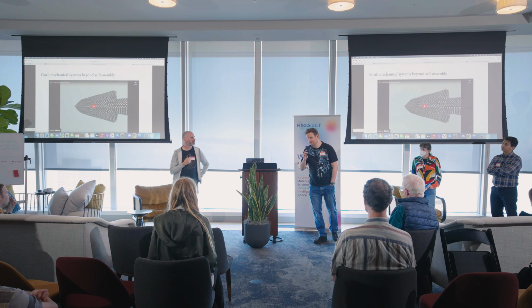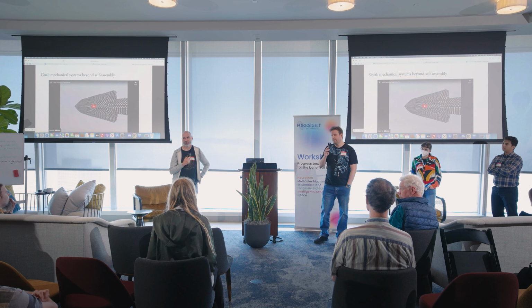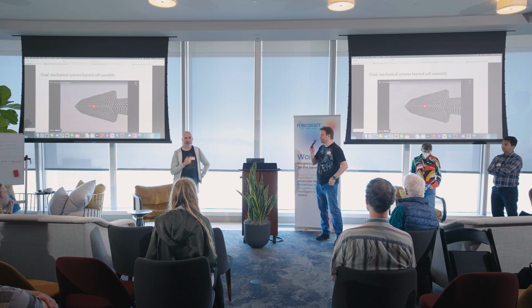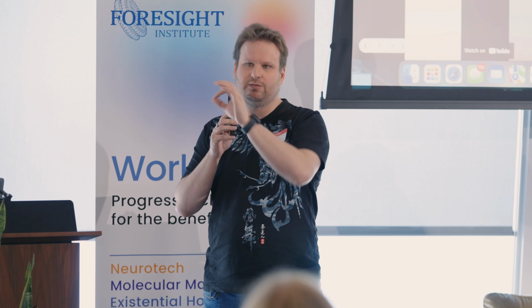That's a great question. We thought about that a lot. Because otherwise you have the piston and the block just glued to the surface. They're all synthesized on the surface, but yes, you need mechanisms by which you can break them off the surface. And typically that would be done by having a much weaker bond to the surface. So these are all diamond for a reason, because diamond is ridiculously strong. And if the bond to the surface is with some other material, then you can break it off without breaking the part itself. That was in theory.